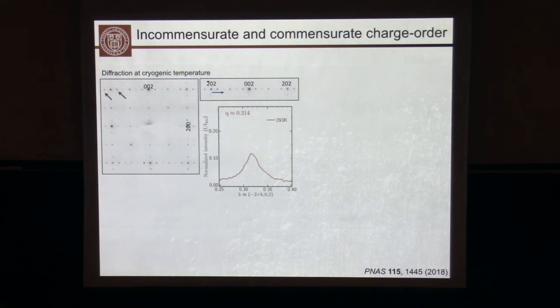We are also not the first ones who have looked at cooling. Lots of experiments have looked at cooling, especially those that average over tens of nanometers, microns, or bulk samples. In diffraction, you can do this already. Remember, this is a diffraction pattern, and we're going to look at these spots now, and see how those spots that encode our ordering change as you cool.